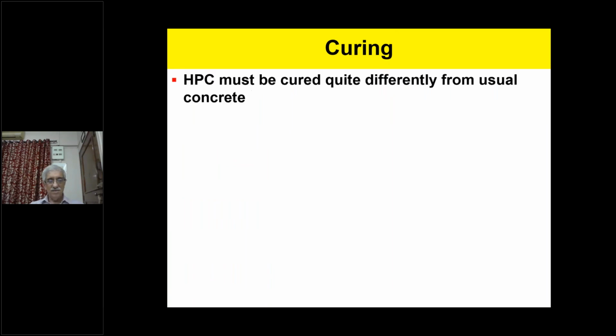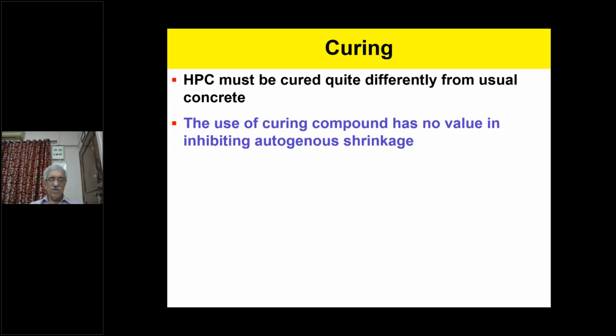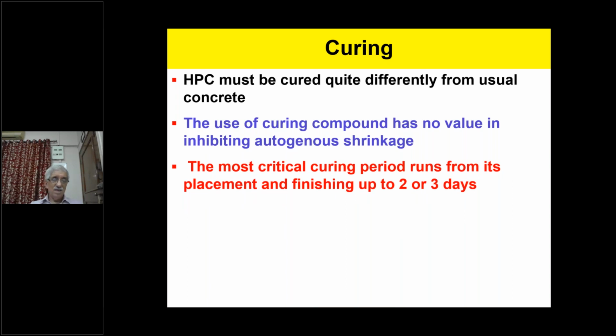Last thing, curing. High performance concrete must be cured quite differently from usual concrete. The use of curing compound has no value in inhibiting autogenous shrinkage. Now, generally, the curing compounds are used so that they inhibit autogenous shrinkage. But in this case, when the concrete is very high strength, it is strongly recommended to do wet curing and not use curing compound. The wet curing can be done for the first 2 to 3 days of placement and finishing, and later on you can continue doing curing with curing compound.